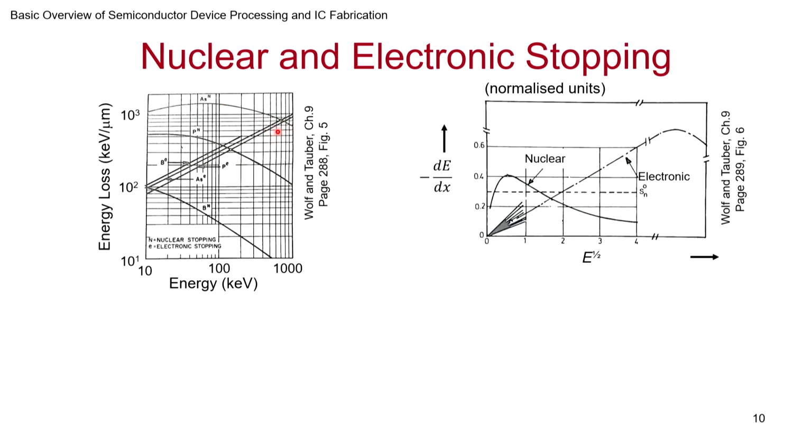And then eventually you will find that when you go for very high kinetic energy, that means it is moving with a very fast velocity. Under such situations, even for the heavier atoms, the nucleus is not able to stop it, because by the time the nucleus potential is going to affect it, it has gone past it. So, the screening will happen. It will be going very fast. So, as a result, you will find that electronic stopping will dominate if you implant with a very high energy. This is not something very strange.